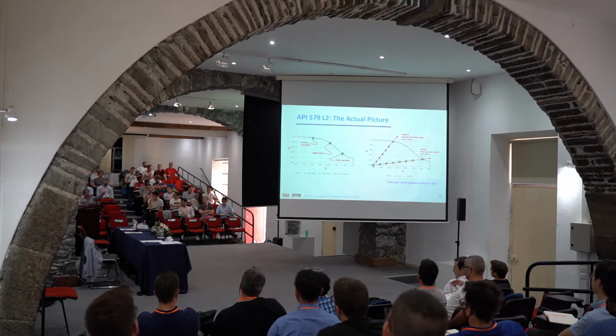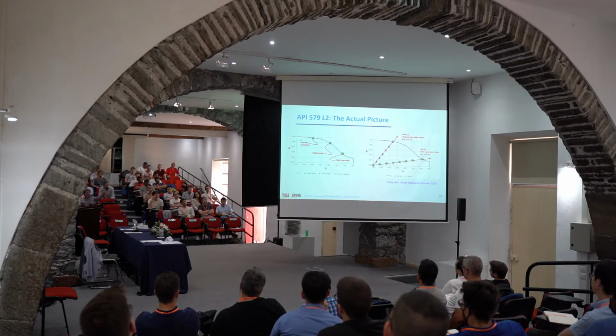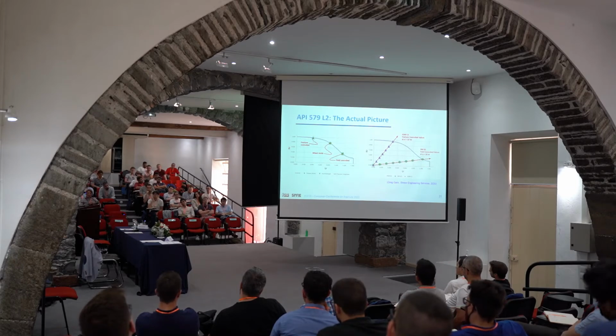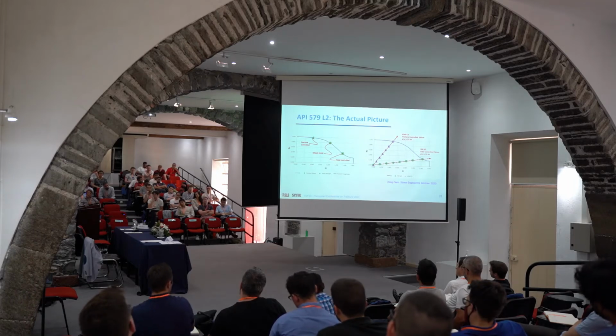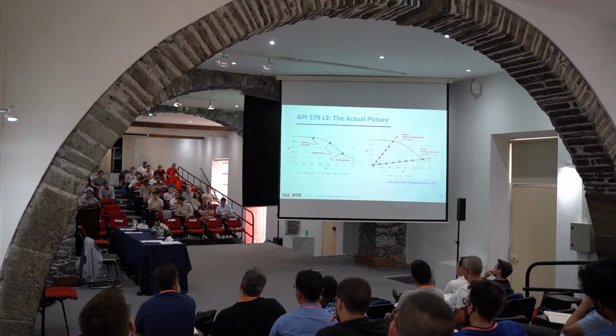There is something I don't understand here. If we are at the very right of the FAD, it's general yielding. Yes, on the right, here is yielding. Then the K factor doesn't mean anything normally, because you can only apply the stress intensity factor if you have limited plasticity. Very good question. Actually, since the procedure is very conservative, it ignores the so-called size requirements for K control. You are familiar with ASTM E399, with very severe conditions for ensuring that this is linear elastic. This ignores it, because it's supposed to be conservative.